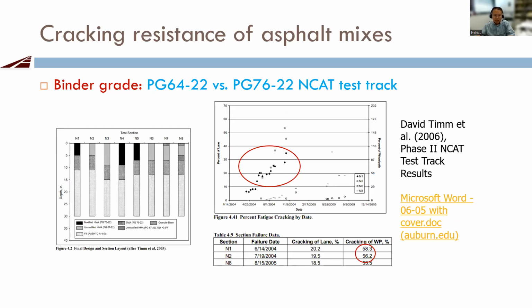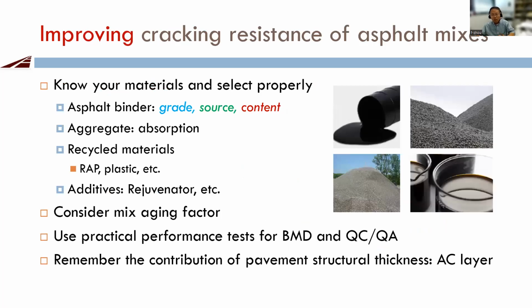So another example, this is from the NCAT test track back in 2006, 64-22 versus 76-22. Sections N1 and N2 have exactly the same pavement structure, same asphalt content. The only difference is changing 64-22 to 76-22. But if you look at their fatigue cracking, it is basically the same. So that really reminds us there's no guarantee we can improve cracking resistance when we go from 64-22 to 76-22. But that doesn't mean 76-22 has no benefit. They do have benefit for rutting resistance and for cracking resistance, but you have to use it in a correct way.